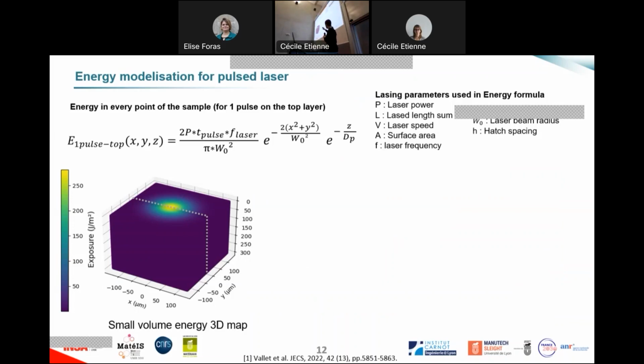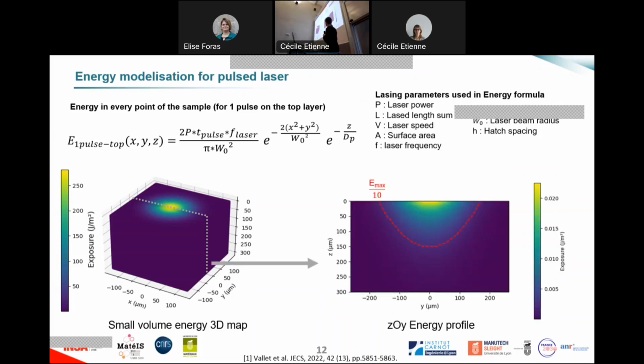And you see that you have a diffusion pattern when you throw a pulse. At 100 micrometers in X and Y, you have an effect. You also receive energy from this pulse. And you can see when you take a cross section of it that you have a tenth of the energy received at even 150 micrometers. So it means 6 layers. It's pretty impressive, and it permits us to continue to polymerize the lower layers, to have a good bonding between the two layers, and to have a good surface state and better properties than what we can achieve with other techniques of 3D printing.